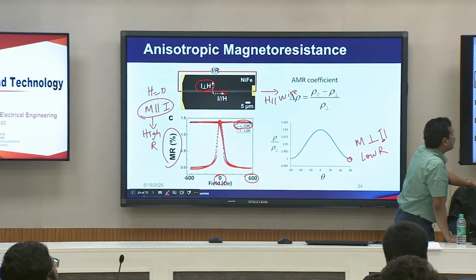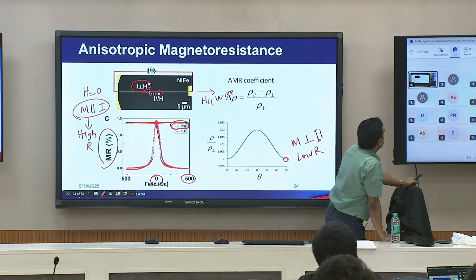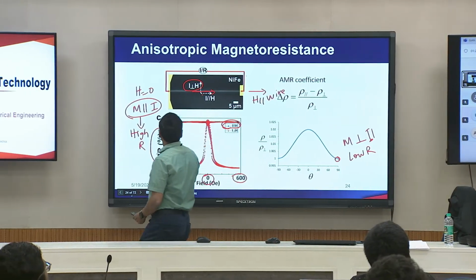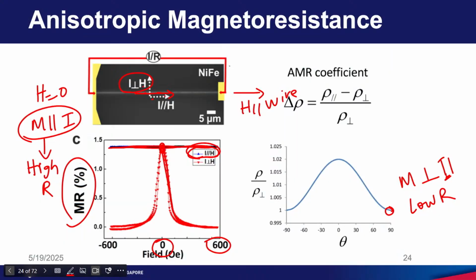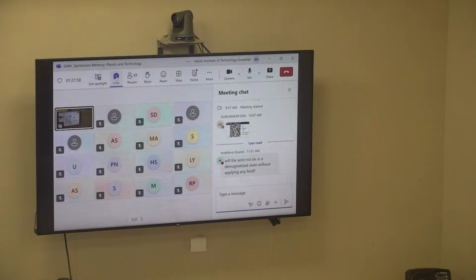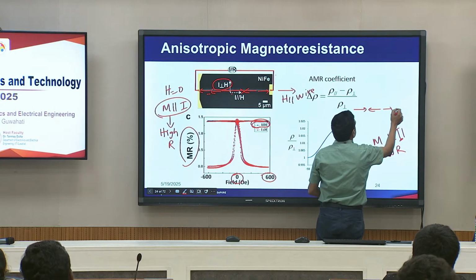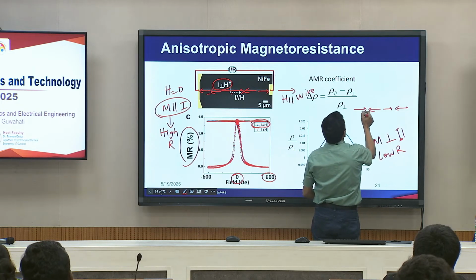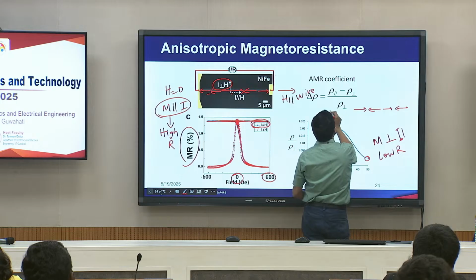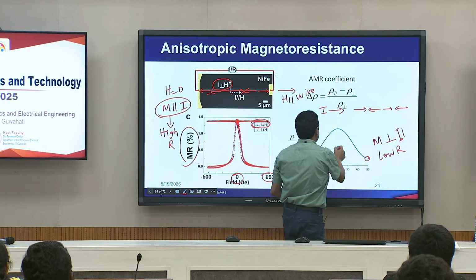Will the wire not be in demagnetized state without applying any field? Yeah, possible. In the demagnetized state also, still the magnetization will be parallel to the current. I mean you may have domains, so some domains' magnetization will be like this. So, you will have different directions, but still magnetization is parallel to the current. So, you will have high resistance. So, your demagnetized state will still be like this. Again, all these magnetizations are parallel to the current direction, so the resistance will still be high.